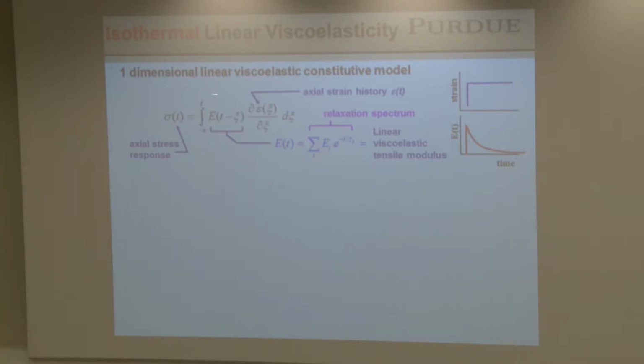The simple models that we've talked about are what are called the linear viscoelastic constitutive model. And what this is, this is the stress response to a strain history. And the material property here is called the linear viscoelastic relaxation modulus. And so we usually express that as a sum of exponentials. And that's the way this is, minus t over a relaxation time for the material, tau sub i. That's a way we describe the material, okay?